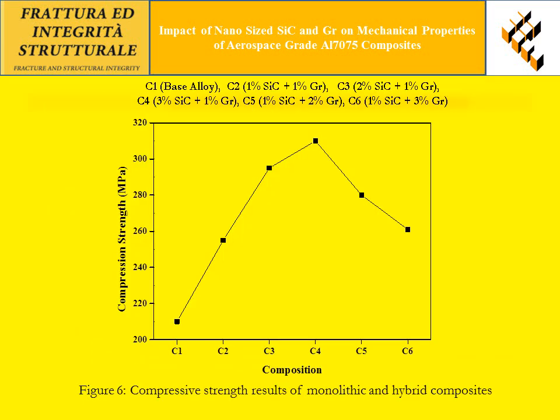The figure shows the compressive strength of the base material and developed hybrid Metal Matrix composites. From the outcome, it is observed that compressive strength has been increased by increasing the weight percentage of reinforcement, generally due to the presence of hard ceramic particulates. Further, the compressive strength has been decreased by increasing the weight percentage of graphite, because graphite is a solid lubricant which has a negative impact on the strength.